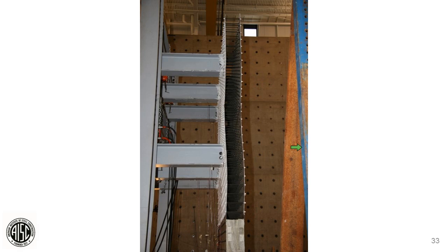There's a paper and some research that was done by Purdue that they've now published, which has prescribed simple methods to calculate the critical buckling stress for a composite plate shear wall panel. As long as you're outside of that buckling stress, what we found is that we didn't see much distortion at all. In fact, we used 1/2 inch plate pretty much throughout. They placed concrete in a floor-by-floor manner, so only a hydrostatic head of, let's say, 14 feet nominally.